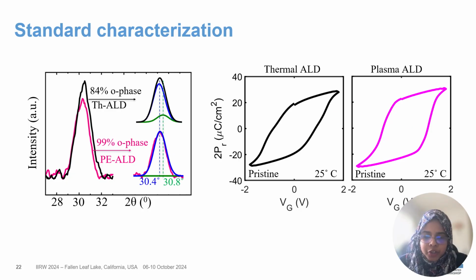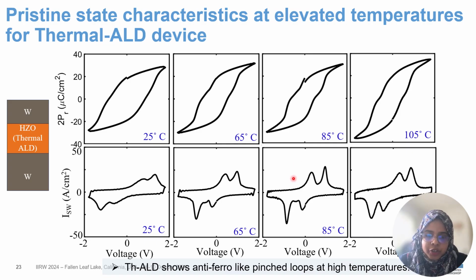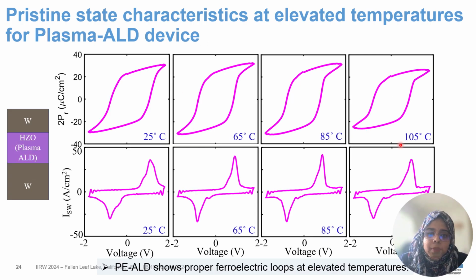Now this was at room temperature. Let's see what happens when we go to higher temperature. These plots are coming from the thermal ALD device, measured from 25 to 105 degrees Celsius. As soon as we enter the high temperature operation regime, the PV loops of this device get more and more pinched. And if we look into the current characteristics, we see more prominent double peak behavior, which shows an anti-ferroelectric behavior at higher temperatures. Now, if we look into our plasma ALD device, we are seeing something completely different.